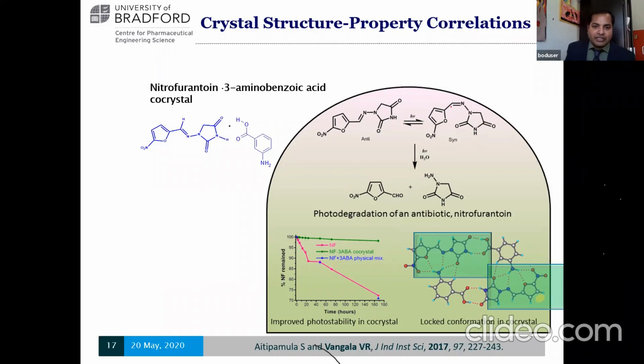So when we prepared the co-crystal of nitrofurantoin with 3-aminobenzoic acid, what happened was, very interestingly, complete stabilization of the co-crystal, whereas nitrofurantoin degraded to the same extent. So then we tried to understand, can we correlate it to the crystal structure properties at all? When we looked at the crystal structure of 3-aminobenzoic acid, which is bonding to the nitrofurantoin through various heteroatoms, oxygens here, nitrogen and oxygen here.